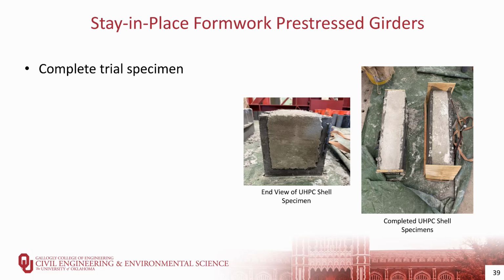We actually didn't, because you can go back to the concrete shell to show those mechanical anchors if you want, Doc. Yeah, so the second specimen that we cast did have grooves that were formed into the side, so you can see them in the foam here. And over here on the right, on the completed shell, you can see the ridges in the UHPC that were formed along the sides and the bottom of the specimen. But in this other one, it was smooth on both sides, and so we didn't have any kind of mechanical connections on those.